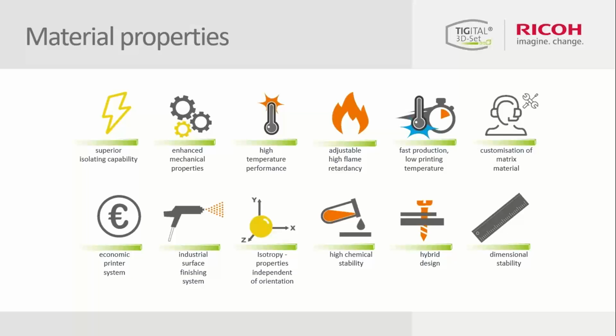And as I mentioned already, we can customize the products to your needs. The advantage of the low printing temperatures also gives you the opportunity to use economic printer systems. And as we also told already, the surface finish of our materials is really easily done, because we can adjust the chemistry of our printed parts to the chemistry of the coatings, in our case the powder coatings, and the attachment between the coating and the printed part is enhanced because of the similar chemistry, and you can reach a high level of surface finish.